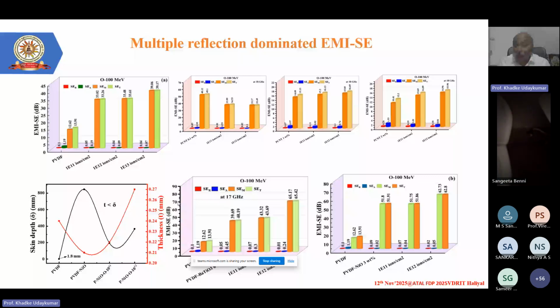But our thickness is in terms of microns, and we observed that the skin depth for the combination of iron and the PVDF composites is very large compared to the thickness of the material. So the thickness is lesser than the skin depth. Obviously, when the thickness is lesser than the skin depth, the contribution from multiple internal reflection will be more dominant, and that is what we observed.